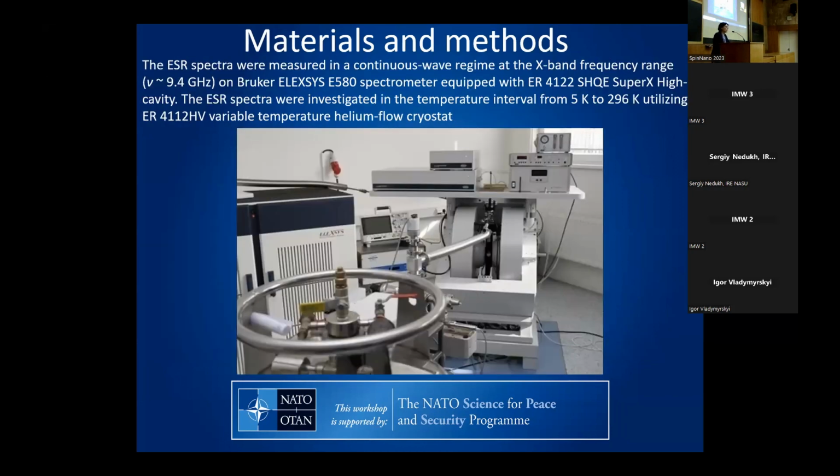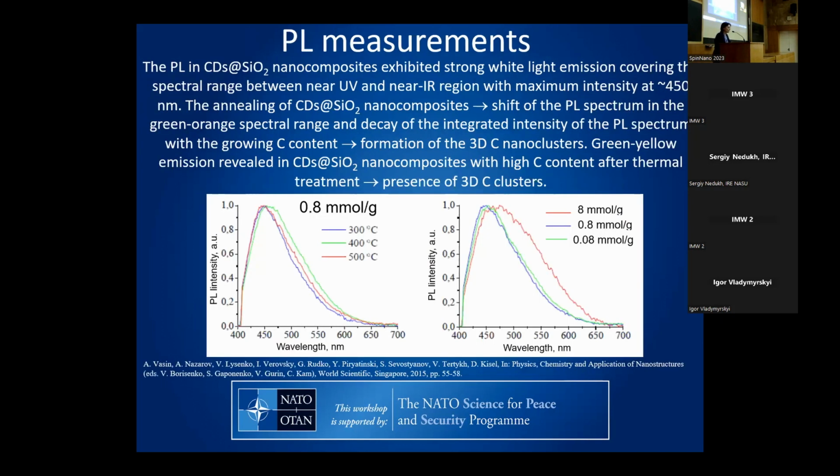The EPR spectra were measured in continuous wave mode at the X-band frequency range on a Bruker Elexsys E580 spectrometer in a wide temperature range from helium to room temperature using a helium flow cryostat. Prior to EPR measurements, the photoluminescence characterization was done.